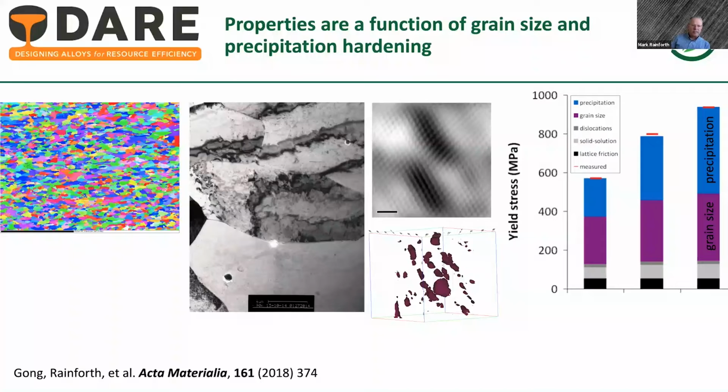So the microstructures we get from this are really rather beautiful. We get a relatively fine grain size in a largely ferritic matrix. Grain size typically of about 2 microns here. The key to this is developing a very fine precipitation of vanadium carbides in this case. It can also be done with titanium carbides. You can see just about within these images the very fine distribution of the carbides aligned in these beautiful lines showing interphase precipitation. They are extraordinarily fine if you get the process conditions correct.